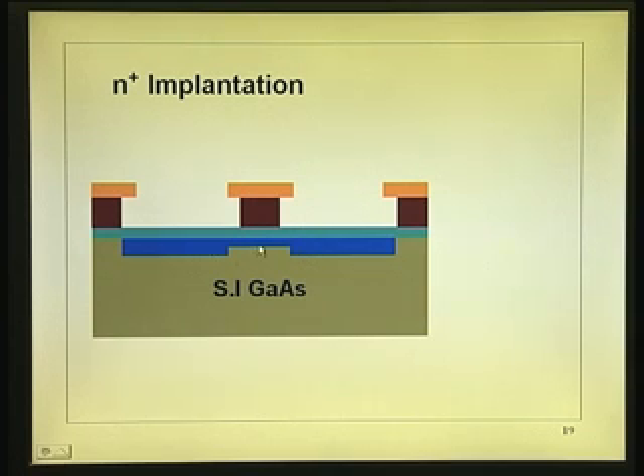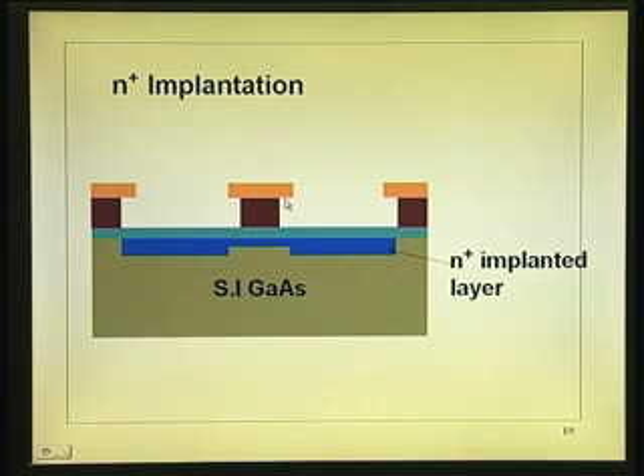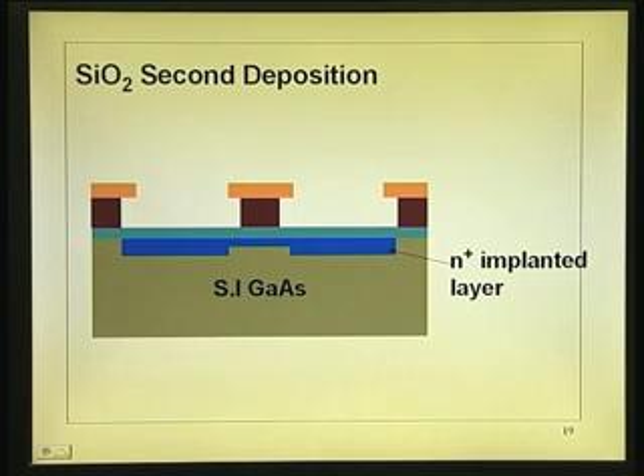So, this is the channel which has a low dose of 10 to the power 11 or 10 to the power 12, this is 10 to the power 13 per centimeter square dose, very heavy dose at 200 keV, so that you can go deeper. Then, I got now a channel region, if I can put the metal here, there is a gap this much, which corresponds to this undercut. That undercut can be precisely controlled by etching time. N plus implanted layer. Now, just notice what you do is deposit another layer of silicon dioxide. You can do that at low temperature, plasma deposition, 200 degree centigrade you can deposit PECVD silicon dioxide.